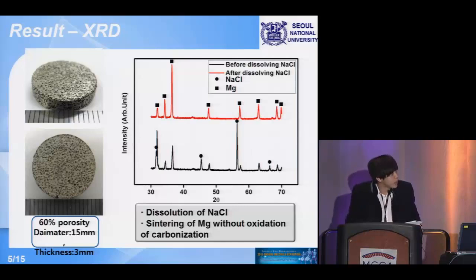This is the bare porous magnesium with 60% porosity, and this is the XRD result before dissolving sodium chloride and after dissolving sodium chloride. As you can see, the sodium chloride peak disappears and only sharp magnesium peaks can be detected, which means that sodium chloride has been dissolved and magnesium has been sintered without any oxidation or carbonization.